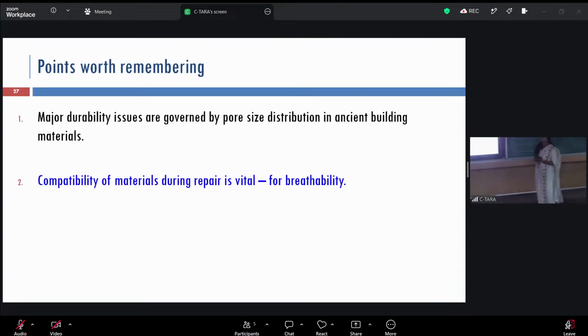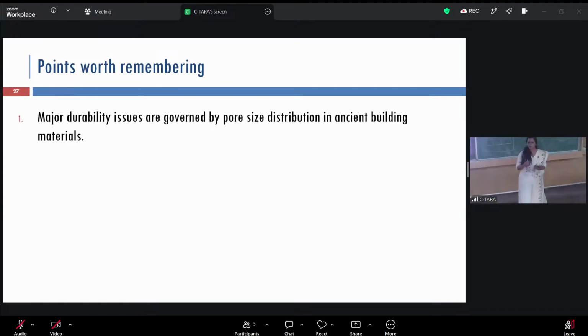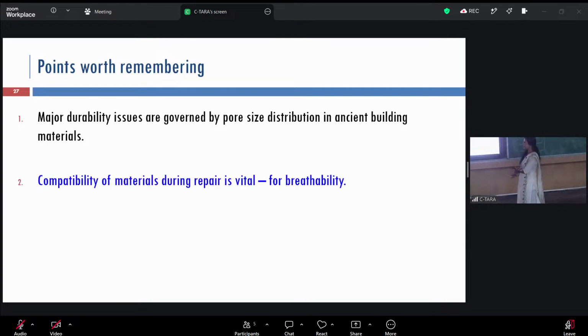If I want you to remember 3 points from this lecture, that would be, most durability issues are governed by pore size distribution in materials. It's not chemistry of the material. It's not because marble is more reactive. It's because of pore structure of the material. You choose pore structure according to the exposure condition.